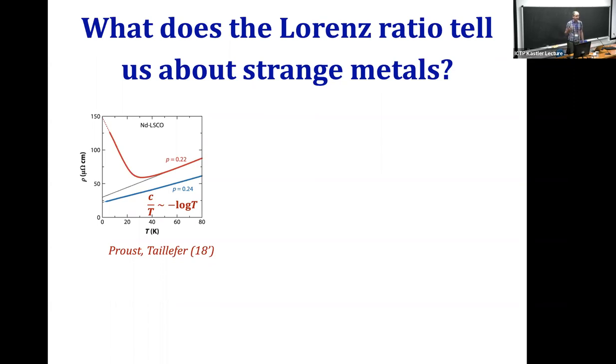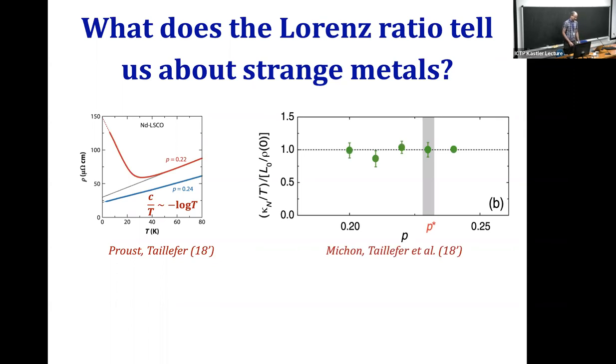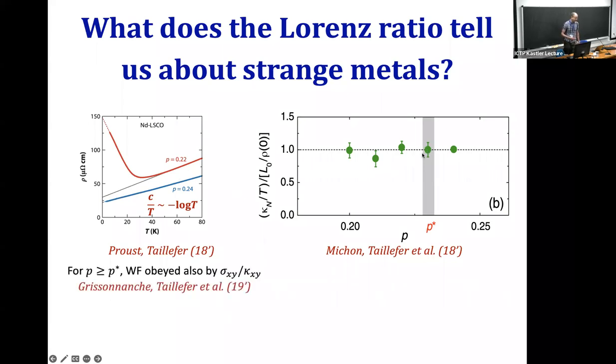And the question is, what can we learn from the Wiedemann-Franz ratio on this behavior? It turns out that at the lowest temperatures measured, surprisingly, the Wiedemann-Franz law is actually obeyed within a few percent in this system. And most strikingly, even at this magic doping, this critical doping, when the resistance is linear down to the lowest temperature, the Wiedemann-Franz law is actually obeyed. Okay, it's also obeyed for the transport coefficients sigma xy and kappa xy.